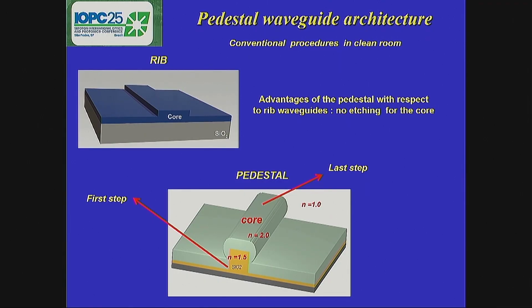And then we used another alternative, which is the pedestal waveguide. In this case, the first step is the preparation of the pedestal that's shown here in yellow. It's a silicon dioxide pedestal prepared in a clean room, and the last step is the deposition of the core of the material. So you can, in this case, use any material you want. You have more flexibility than in the other case. Just for those that do not know, the core is the place where the light is going to be guided.